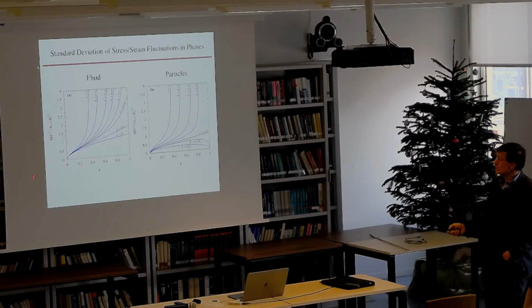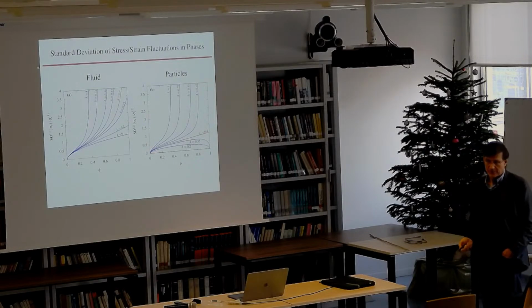You see that the fluctuations increase with the volume fraction. For lambda equal to 0, the lower bound, the fluctuations actually are bounded in the matrix phase, and they're exactly 0 in the inclusions.